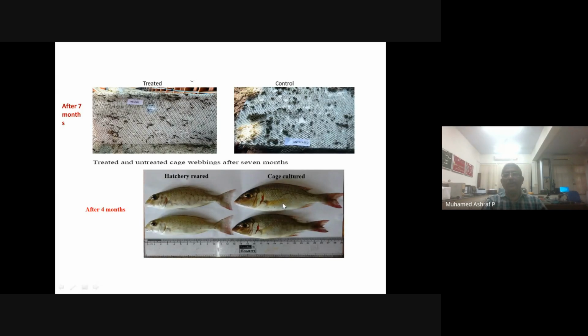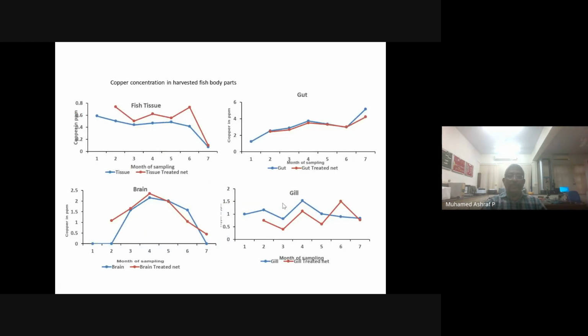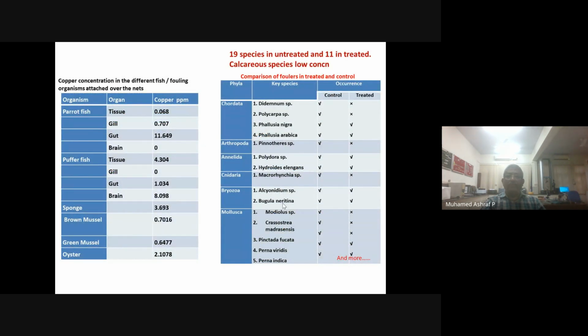We can see that the quality of the fish was very good, and then we analyzed the fish tissues, guts, and gill, everything. We found that none of them had a higher amount of nano copper oxide or copper oxide in the tissues or gill. Then we checked what different types of organisms were present. In the treated one very few organisms were present, but in the untreated one, many different organisms were attached.